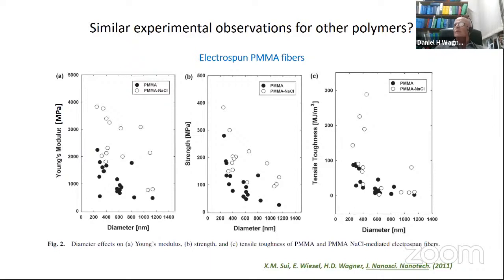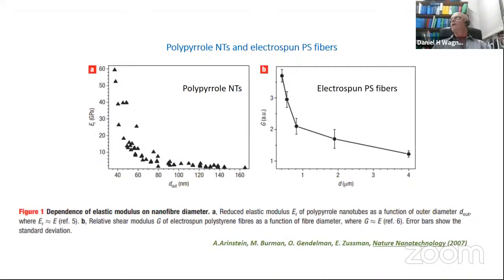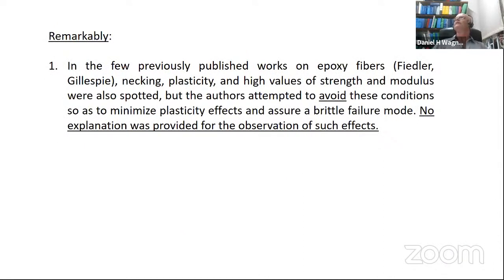There is also another set of data which is not ours. And it's not with epoxy. Well, it is ours actually, but it's not with epoxy. It's electrospun polymethyl methacrylate fibers. And again, we have an effect of the diameter on Young's modulus, on the strength, and on tensile toughness. This is work we did a long time ago, 10 years ago, something like that. And we observed also a size effect for very thin nanometer-size electrospun PMMA fibers, not epoxy. Okay, and then a little bit more: polypyrrole nanotubes and electrospun polystyrene fibers also show a size effect in the range of microns and submicrons for the polystyrene fibers, and in the nanometer range for polypyrrole. So this is really a universally observed phenomenon.